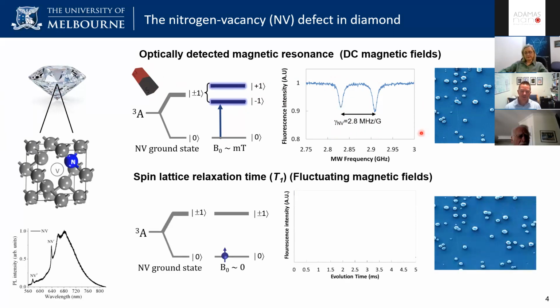The other really useful sensing mechanism that we take advantage of is something referred to as the spin lattice relaxation time. And this refers to basically the spin lifetime of the NV. And so, as I said before, if we're showing green light onto the system, we can polarize the NV spin into the ms equals 0 state. If we turn that laser off, that spin will then start to interact with neighboring spins within the diamond, but it will also interact with environmental spins that are outside the diamond. And so what will happen is that spin will relax to a mixture of these three states.